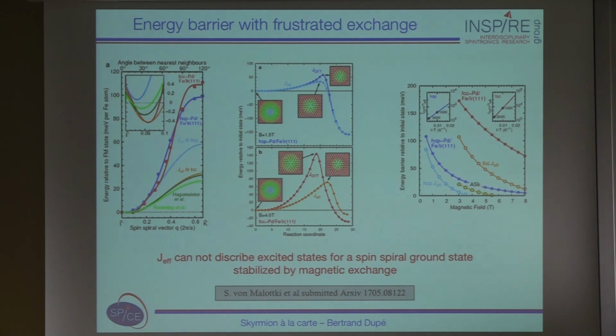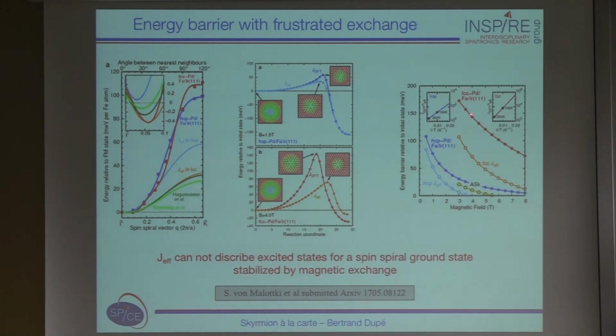Now, if you look at the most frustrated system, which is palladium FCC on iron on iridium 111, in that case, you have a difference by almost a factor of 2 between the barrier with a full DFT coefficient and with only J effective. So if you plot now this energy barrier with a full set of DFT coefficients and just J effective as a function of magnetic field, you see that this behavior is actually constant in a whole range of magnetic field. So if you look at palladium FCC, if you have frustration of exchange, the energy barrier between the skyrmion and the ferromagnet is always higher than this orange curve, which is the J effective for FCC palladium iron iridium. The difference here for the HCP stacking is much smaller than for the FCC stacking.